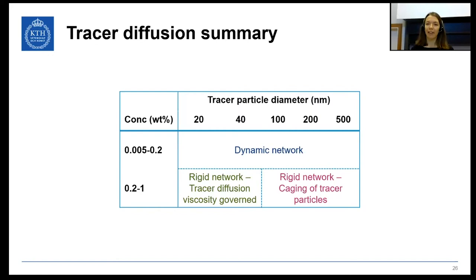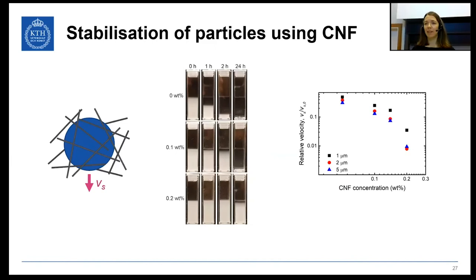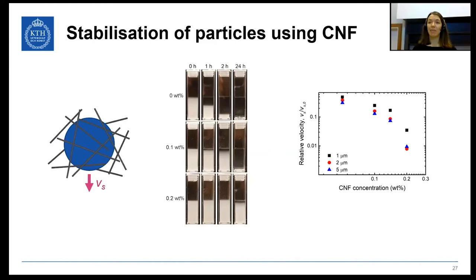We found this caging phenomenon quite intriguing since it appeared at low concentrations — the water content in these dispersions is 99.8 percent. We then studied the sedimentation velocity of silica particles in CNF dispersions and compared it with sedimentation in water. Already at a cellulose content of 0.05 weight percent there was a significant impact on sedimentation velocity, and at 0.2 weight percent sedimentation was considerably slowed down. For the largest silica particles, the sedimentation velocity was only 1 percent of its value in water. These results show that CNFs can be used at rather low concentrations to stabilize other particle dispersions.